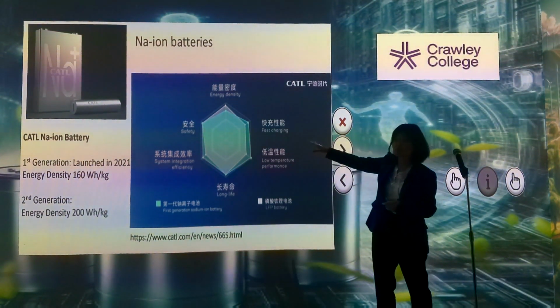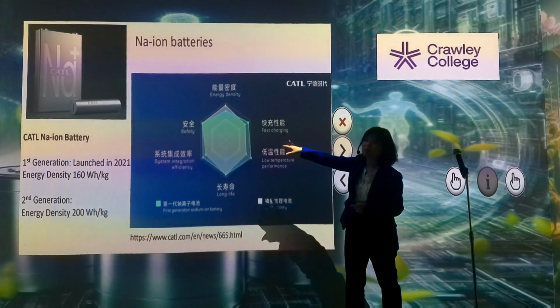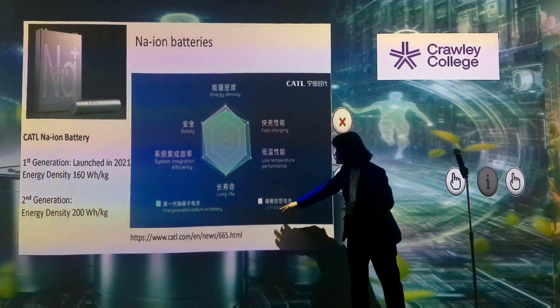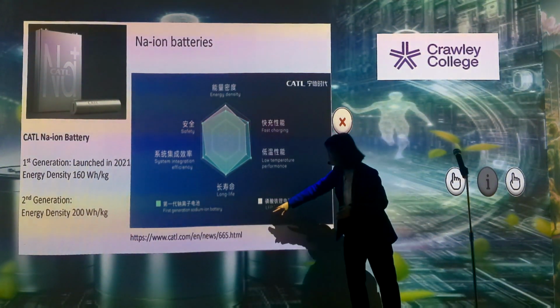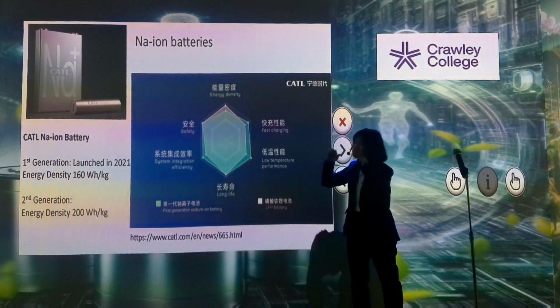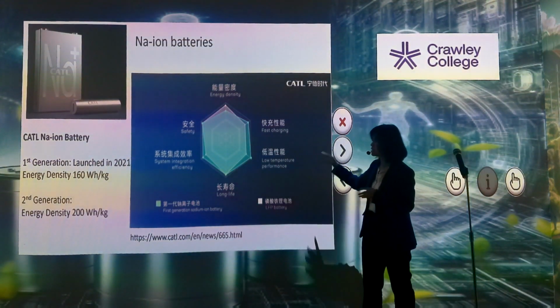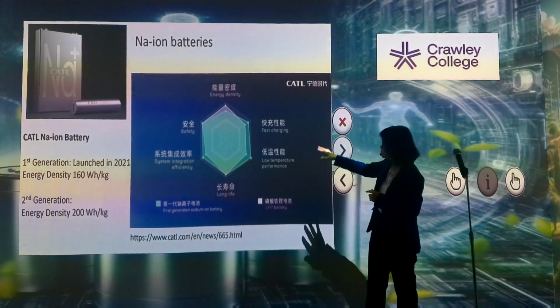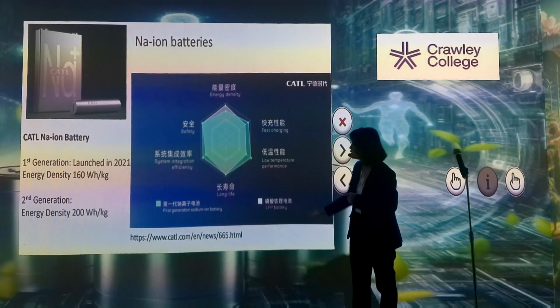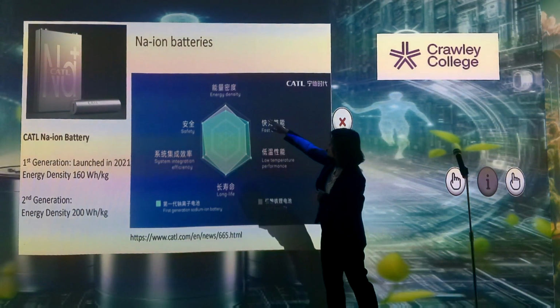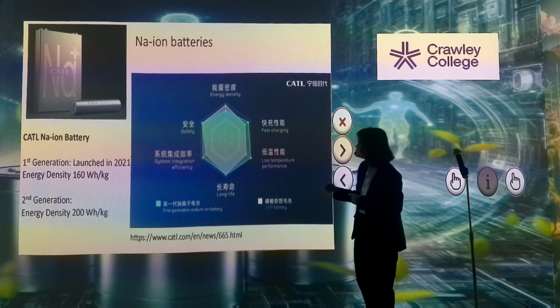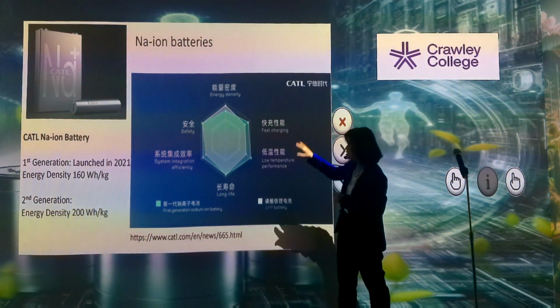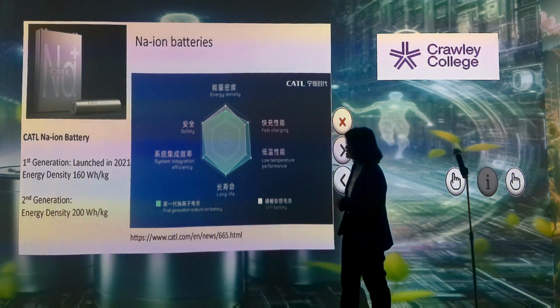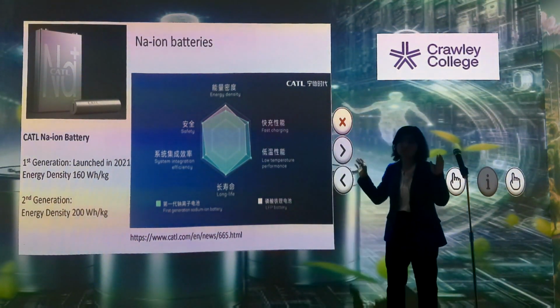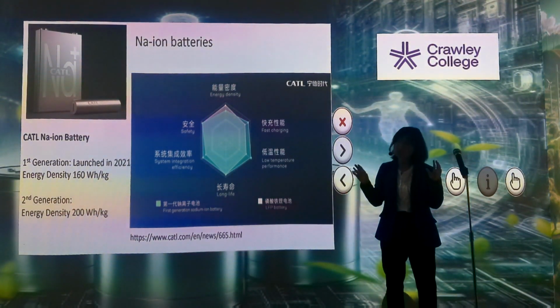And I took this from their website. They try to compare this sodium-ion battery with a lithium iron phosphate-based lithium-ion battery. I mentioned this type of material earlier, that this battery has a relatively lower energy density compared to other lithium-ion batteries, but has higher safety and longer lifetime. If you compare the sodium-ion battery with this type of lithium-ion battery, you can see that the energy density is only a bit lower, but the safety and long lifetime are comparable, and the fast charging and low temperature performance is even better. So it does provide some promise to replace lithium-ion batteries in some applications where you don't require high energy density.